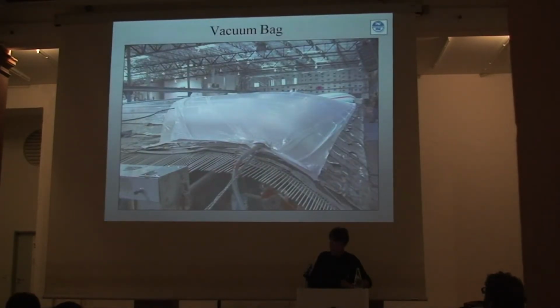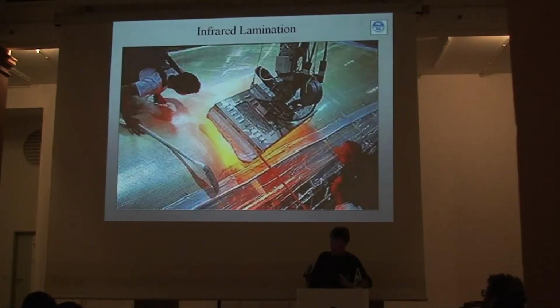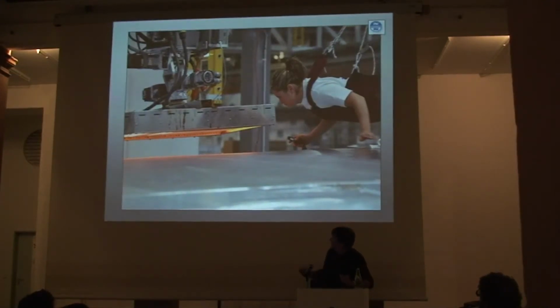There's a vacuum pressure pulled on that sail, and then while it's under pressure and the materials are being consolidated, you pass heat over the surface. It flows the adhesive, which commingles and bonds the fibers to the film. So it's important that it's heated at the same time it's under pressure. And I was looking at the operator. This is what we call an infrared heating system. So there's infrared energy fired into the surface of the laminate. It excites the molecules in the adhesive and heats them up. The operator there has got a little infrared temperature gauge, so they can check that the surface of the laminate is appropriate to make the adhesive flow that's encasing the fibers.